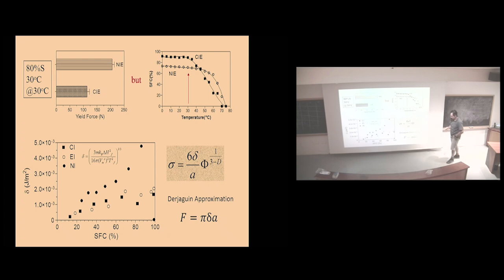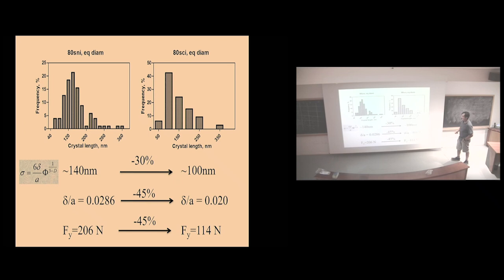This was obtained with the Derjaguin approximation for spheres. And then we also determined the size of the crystalline nanoplatelets. Look at that, the non-interesterified, what is it, around 140 nanometers, and the interesterified, 100 nanometers. So we decreased the crystal size as well. Now, that is not very good news according to the model, because if we decrease the size of the crystal, it should get harder. So that's working against us. The interfacial tension, I thought, we got it. And then we checked the crystalline nanoplatelets, even though you can argue that putting one number to that distribution may be a little silly thing to do. But we take the median of that.